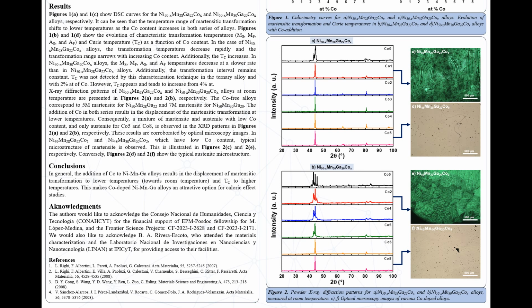These results are corroborated by optical microscopy images. In this alloy and that alloy, which have low cobalt content, the typical microstructure of martensite is observed. Conversely, in Figures 2D and 2F, we can see the typical austenite microstructure.